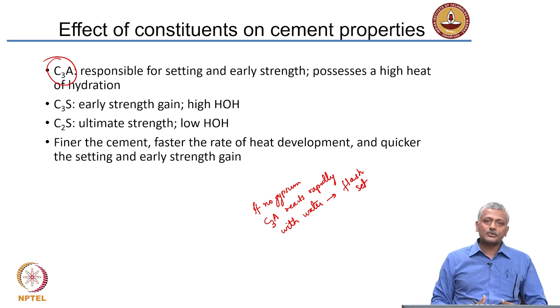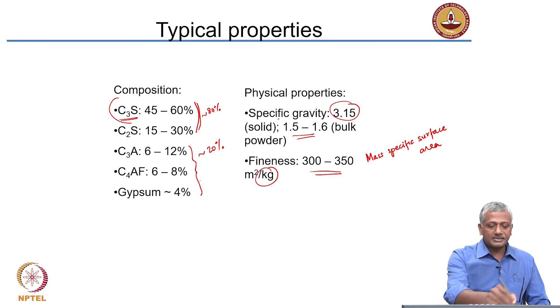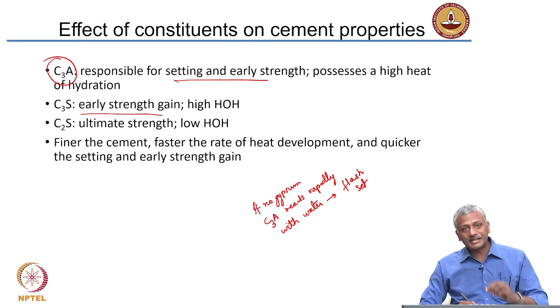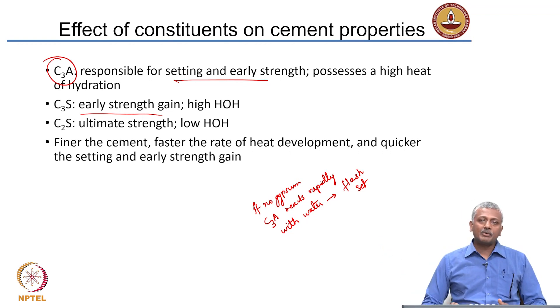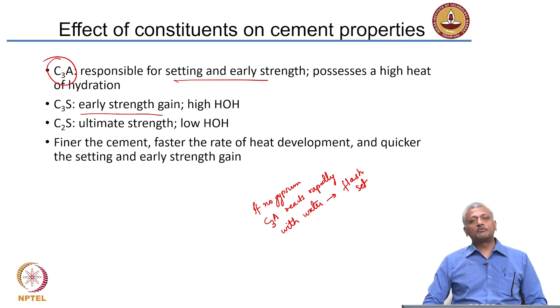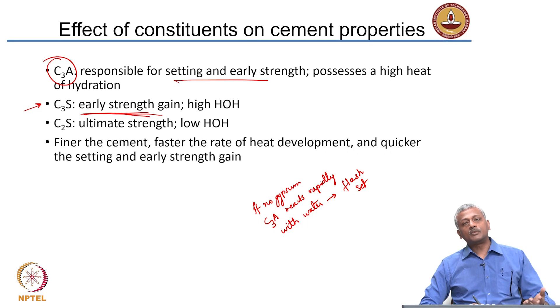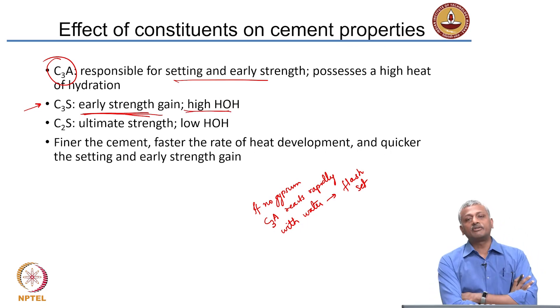Nevertheless, the interaction between gypsum and C3A still gives rise to some early strengthening and setting of the cement. Since cement contains more than 50% C3S, it is also responsible for early strength gain — that is why we want more of it, so that concrete can gain strength early. Modern construction projects want to finish fast, so the cement should be rapidly strength gaining. C3S is the compound primarily responsible for high early strength, but it possesses a high heat of hydration, meaning it evolves heat rapidly and the potential for cracking could be significant.